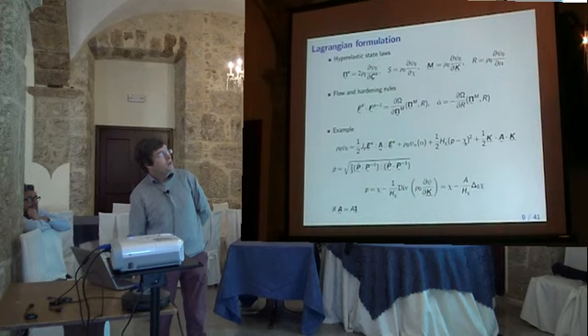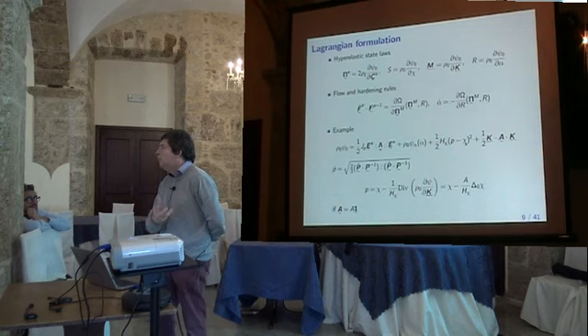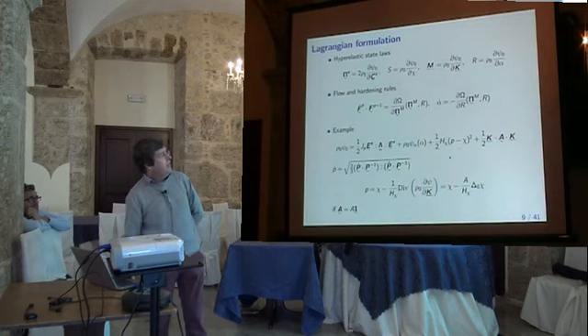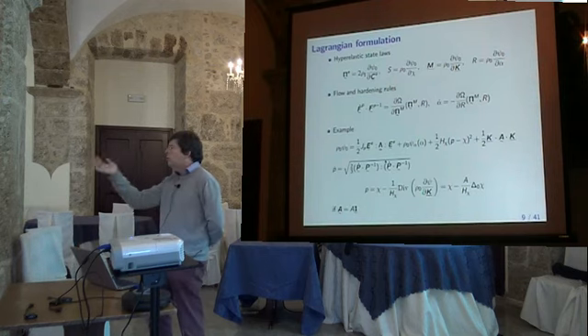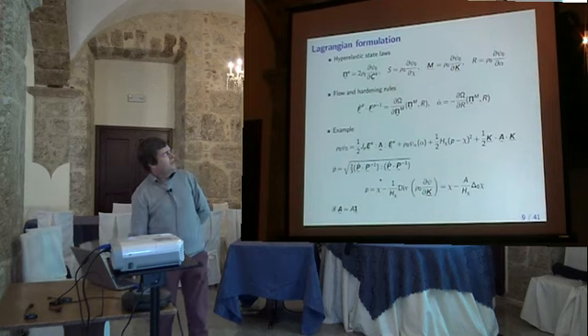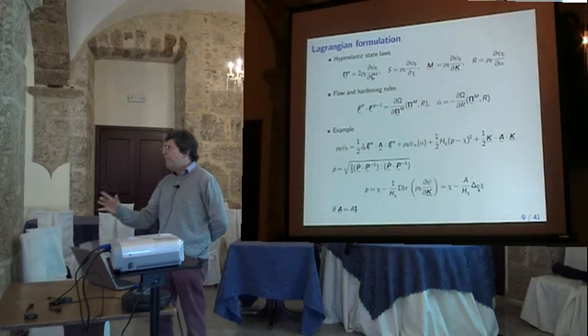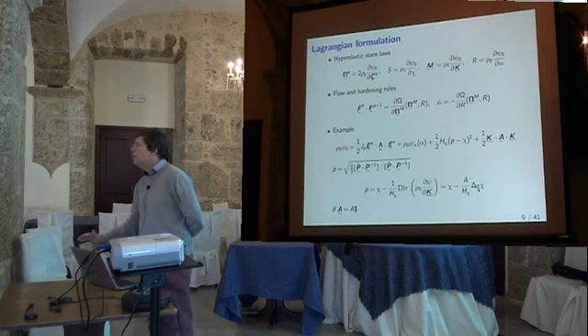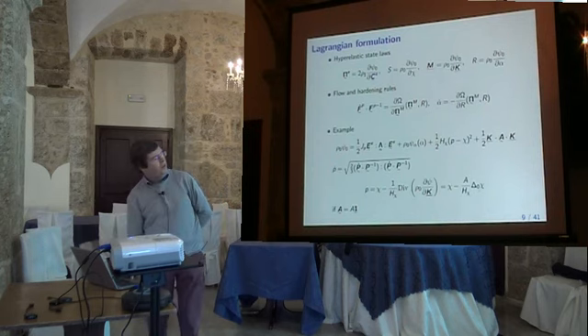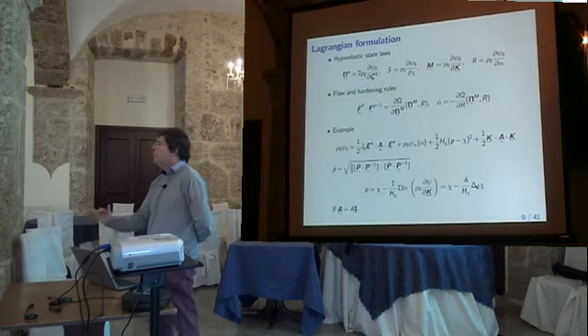So now the meaning of chi is really something plastic due to this constraint. And then you see I have taken a norm of the plastic strain rate here. And if you plug all this in and calculate everything, you get this equation for the micro deformation, which is a partial differential equation like this, with the Laplace term in the Lagrange framework. So the Laplace here is a Lagrange Laplace. So this is what you find.